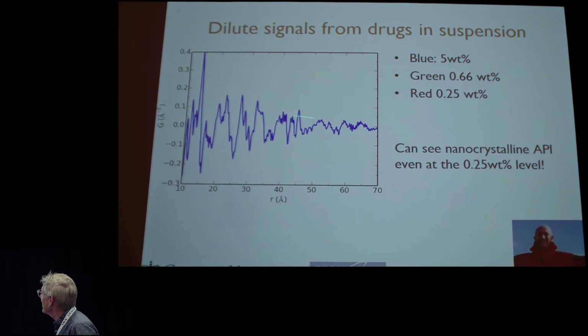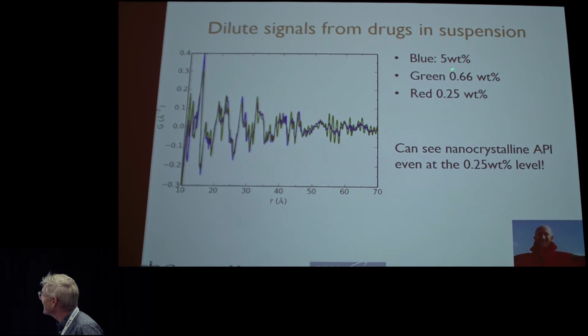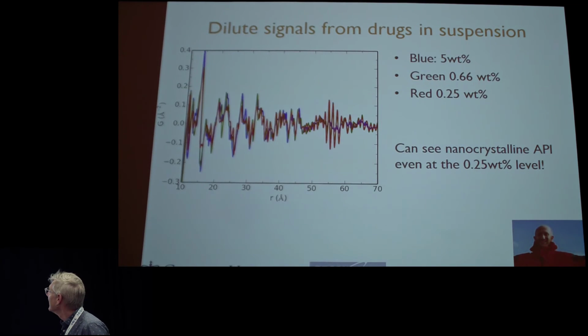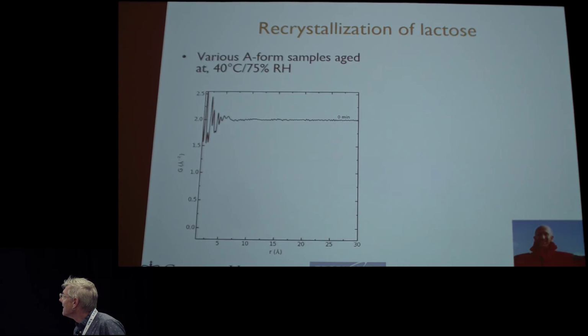But then we can notice this is the 5% weight% of the drug. But this is actually 0.66 weight%. And you can see we're reproducing the signal very, very beautifully. And finally, 0.25 weight%. It was a big surprise to us, and it came about because of some software developments that we've been doing. We hadn't intended the software developments to do this, but they did this. So we can suddenly look at very, very small signals, 0.25 weight% of an organic in water. So we're very excited about this. It opens the door for all kinds of studies.